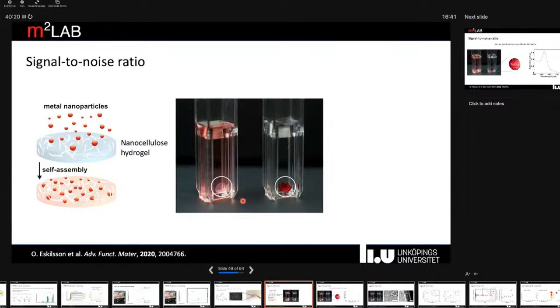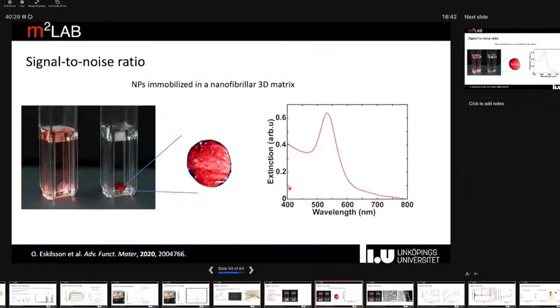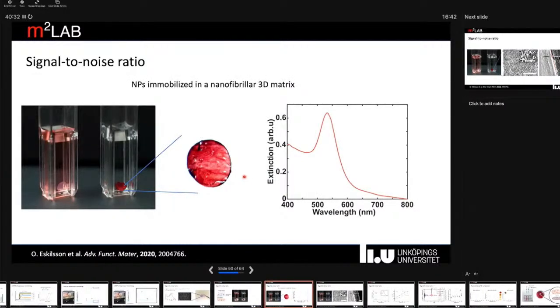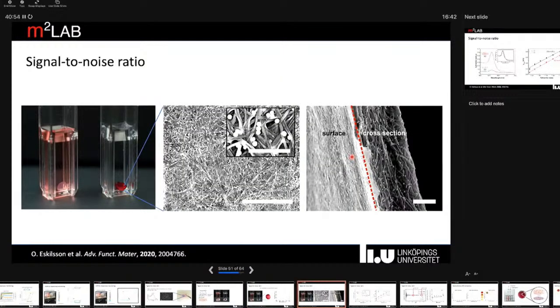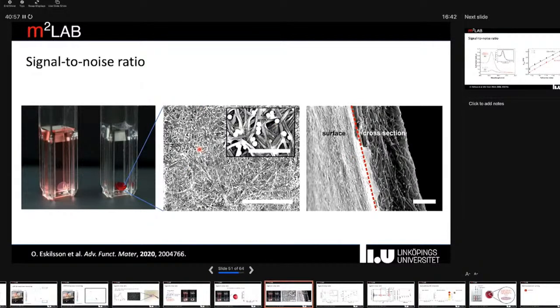So after some optimization, we were able to essentially make all these particles go from being suspended to being adsorbed in this membrane. And as you can see here, we end up with a substrate that is not faint pink, but bright red. We can also increase this intensity quite a bit more, but then you start to get a broadening of the plasmon band. But in this case, we have a very well-defined plasmon band, and this is due to the particles being fairly well distributed within this three-dimensional matrix, both on the surface but also throughout the entire volume of this hydrogel.